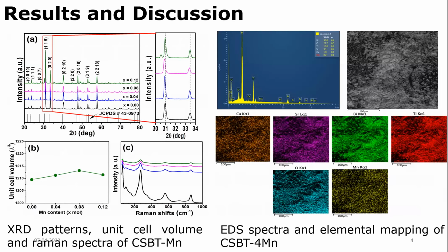The results and discussion are as follows. First, you will be seeing the XRD graph. The highest peak has been observed at 119, which matches what is expected of the exclusive feature of BLSFs. Here we can see that the unit cell volume with the concentration of 0.08 is higher. Raman spectroscopy has been done in order to observe the phonon modes at different wavelengths. And here you can see the EDS spectrum and elemental mapping, especially for CSBT4MN. Here we can see that Mn is uniformly distributed over the whole composition.